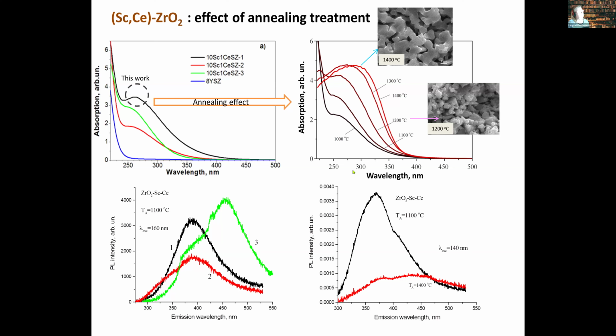In this case, the question was where we stand with structural properties, and whether we can use optical characterization for checking the properties of zirconium oxide. First of all, we did annealing treatment at different temperatures and checked the transformation in optical absorption. You can see that the higher the annealing or sintering temperature, the higher the contribution of different oxygen vacancies. And this band is quite high.